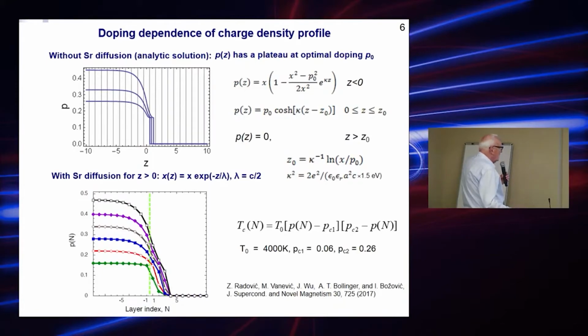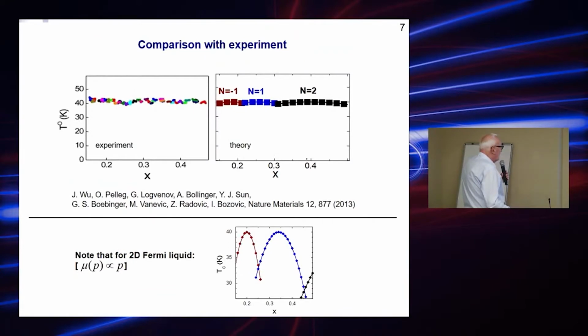Okay, the next slide is experiment and theory. And in theory, we can identify in which plane, copper oxide plane, is realized this maximum temperature superconductivity, depending on X. Okay, and only for information, taking linear dependence of mu on P, the theoretical results is like this for temperature. It's not like this in experiment and the right theoretical explanation.